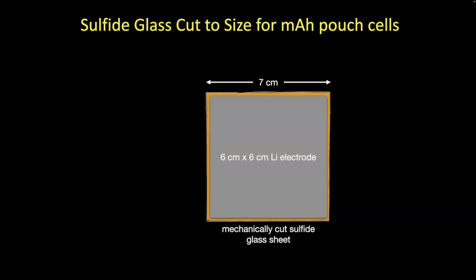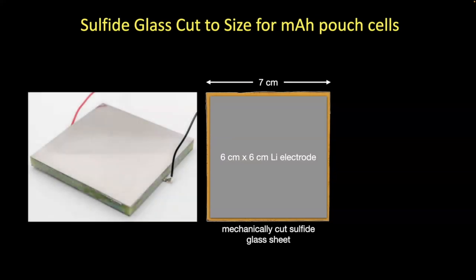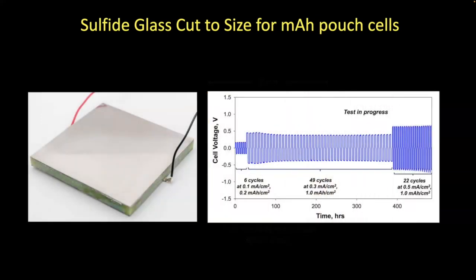We can bond that with a 6x6 centimeter lithium electrode. It's about a 100 milliamp hour cell. We're building pouch cells, and we're just starting to cycle those pouch cells now and build full cells. These are lithium cells, but we're building full cells now. So we're well on the path to getting to, I would say, more commercial type prototypes.